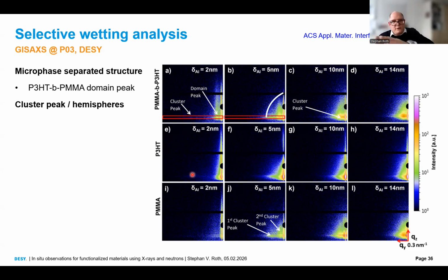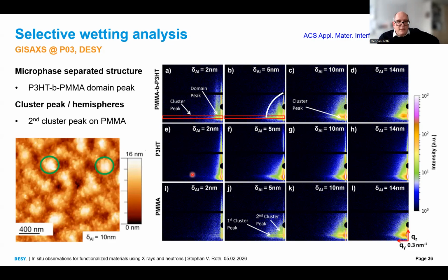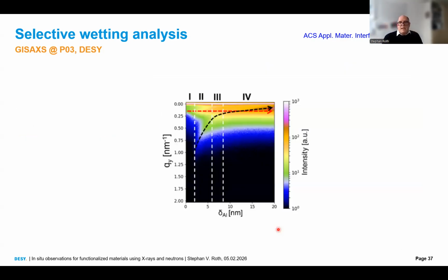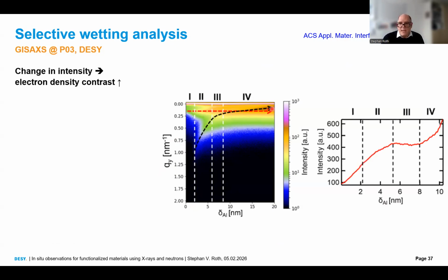And from the overall shape, we can find out that the clusters really grow in hemispheres. You make an AFM image. You see these clusters here, they look round. We know from the GISAXS analysis they are indeed hemispheres. And you see here clusters of clusters, which again make up here a second cluster peak. Good. We can again make a map here. This is the deposited aluminum layer. This is QY, so on horizontal cut and intensity coded. You see here the structure peak of the polymer, and you see here the side peak moving in. These are the aluminum nanoclusters growing on the surface during deposition. And when you follow here, actually, this diblock copolymer peak, you see first an increase in its signal.